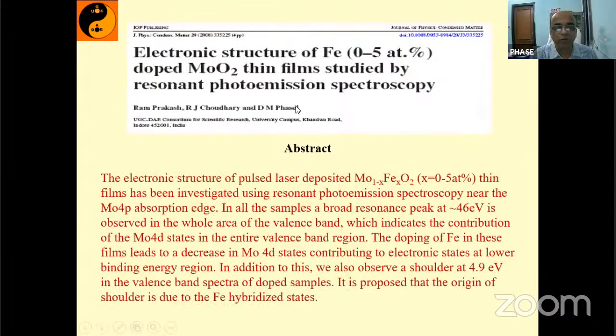Then this is another example. A lot of people are doping samples in some oxides, but you don't know what will happen once you dope the material. Whether it is interacting with the host lattice, or whether it is only acting as an isolated cluster sitting inside the material, or whether it is really chemically interacting with the host lattice. That kind of thing one can find out by using resonant photoemission spectroscopy. So this is one of the examples.